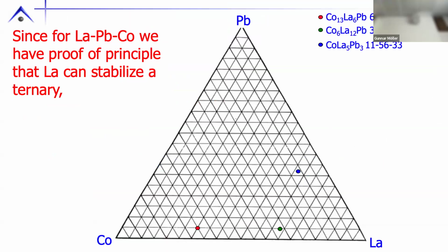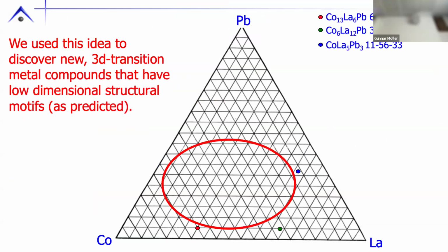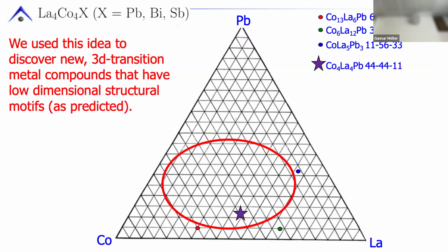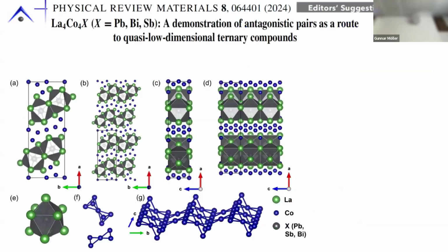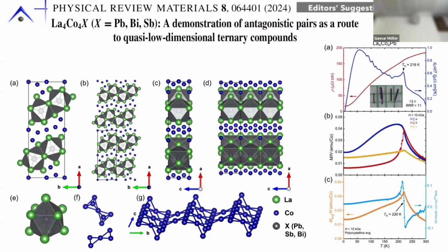And what we decided to do is, since we had proof of principle, we could stabilize some lanthanum, lead, cobalt materials. We asked ourselves the question, can we find others? So we looked in this region. Okay. And indeed, we found a completely new structure, a completely new set of materials, cobalt-4, lanthanum-4, lead. Okay. And what's beautiful is we have these distorted Kagome-like layers of cobalt separated from the lead by the lanthanum. Again, a two-dimensional motif. Okay. And what's even nicer is they're moment bearing. Not surprising. I've packed my cobalt densely enough and it's two-dimensional. I can actually get some magnetism here. And the magnetism looks like it has hints of two-dimensional order associated with it.